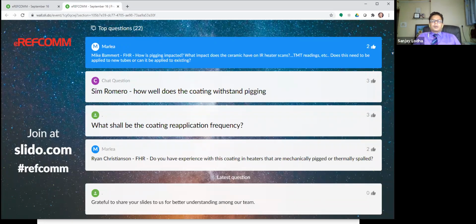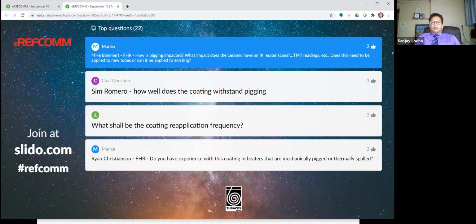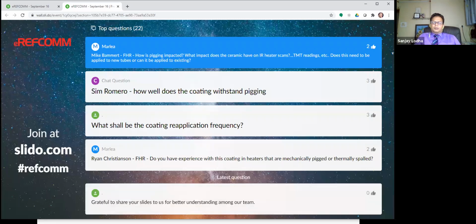And then there was a question: what impact does the ceramic have on IR heater scans? So what you would see in the scanning, as I showed you in one furnace, is that you would not have hot spots. You have a unique, temperature-consistent profile on your heater temperature scans and TMT readings, and it will be a much longer time from your startup run to end of run, even within a smaller temperature window, because you're not coking as much, you're not fouling as much, you're not depositing as much coke. So the end of run is reached much more slowly compared to what it would be otherwise without the coating. And that's how the system works.